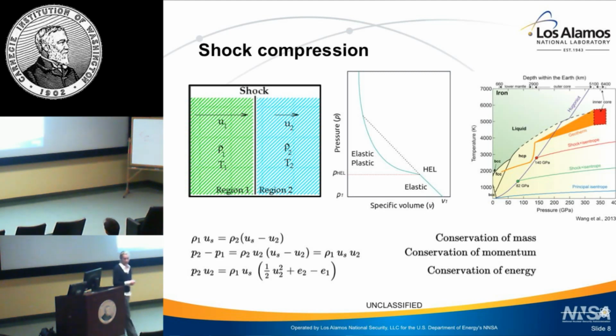So if you send in a shock wave, there will be some material at a particular high pressure, high temperature state on the Hugoniot, and in front of the shock front, you are still at ambient condition, okay? These two regions are in local thermodynamic equilibrium, but at this interface you are far from equilibrium in your material. So exploring phase transitions in this context allows you to look at not only equilibrium or local thermodynamic equilibrium, but also non-equilibrium components in your system. The Hugoniot is not the path that the material takes, right?